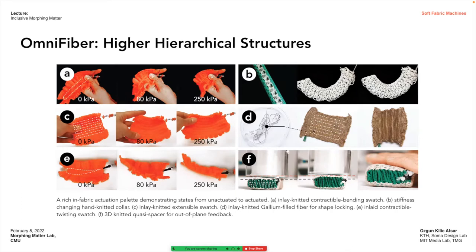As seen in figure D, we use a low-melting-point alloy — in this case gallium — injected into silicone tubing, then pneumatically driven to actuate the fabric sample. When kept in the actuated state at room temperature for roughly half an hour, the gallium transitions to a solid state, locking the shape of the fabric. This is thanks to the unique property of fluidic actuation called a 'catch state,' where no additional energy is needed to maintain the actuated state — you just keep a closed valve.